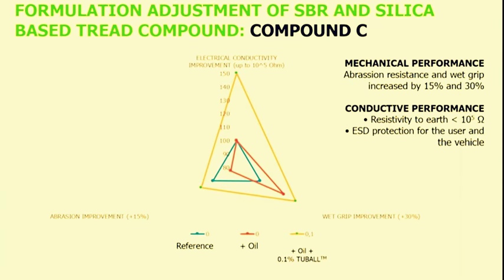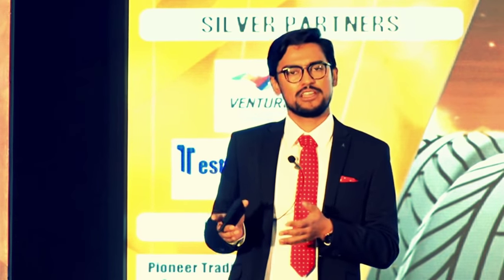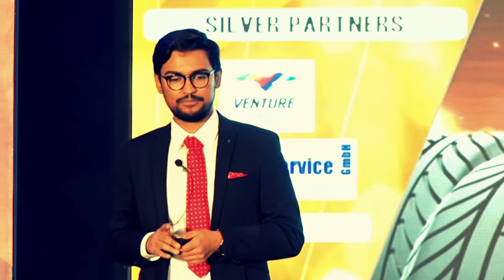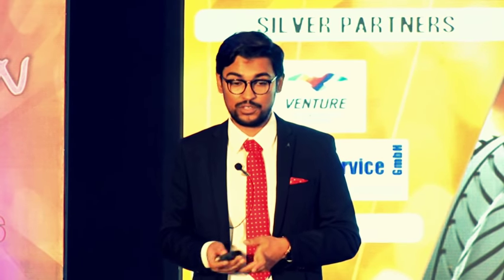This is for motorcycle tires, where wet grip is very, very important. We did two trials, one with only oil, where we increased the oil in the compound, and then we added carbon nanotubes plus oil. Oil we used here as a carrier, and it is worthwhile to mention that this enhanced compound is commercially being used by our own internal manufacturing of UJET vehicles, which is an electric scooter, a spin-off of OCSiAl. So this is a commercial result in front of you. We are using this.